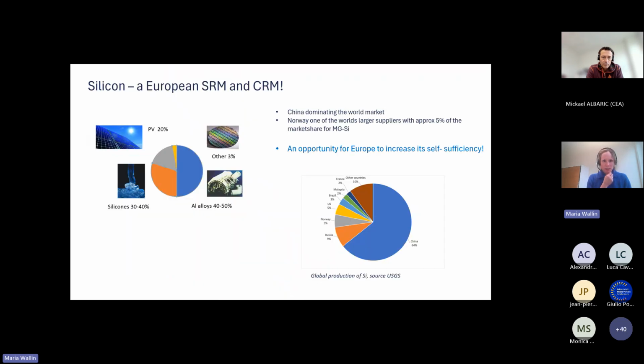And as I said, it's critical for Europe, and it's mainly because we are so dependent on China, about 64%. When I got this map, it was produced in China, and you see Norway, we have a share of 5%, so we are quite important for Europe when it comes to production of silicon. And where you see where it goes, about 20% goes to PV. It changes, of course, all the time. Silicon has a big share, but you can see the aluminium alloys. Lots of the silicon produced is actually used as an alloy element in aluminium.